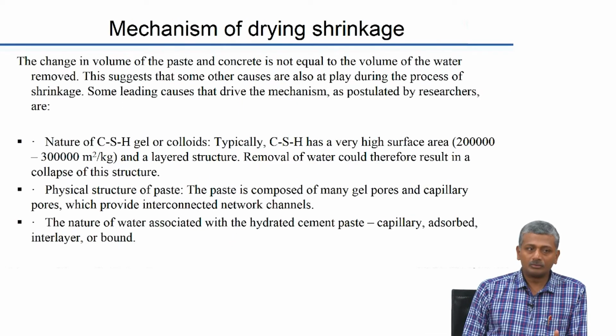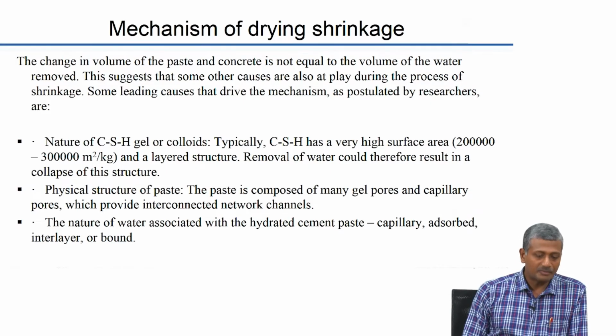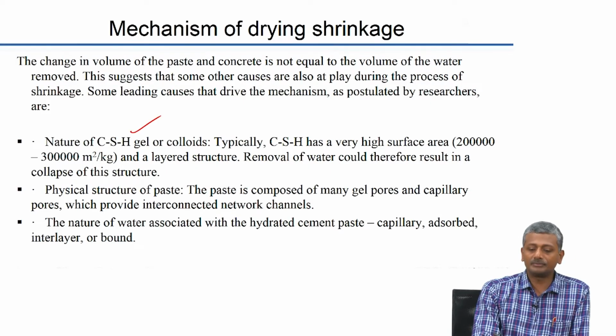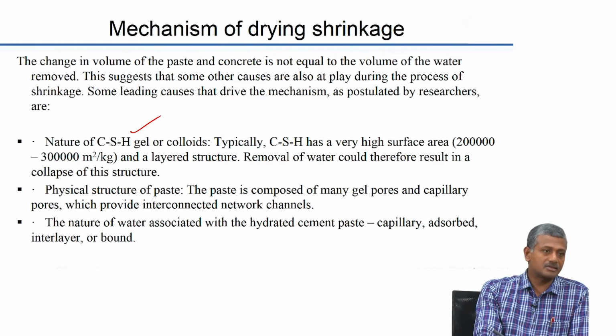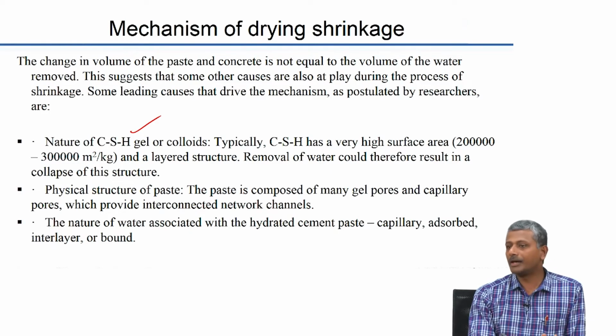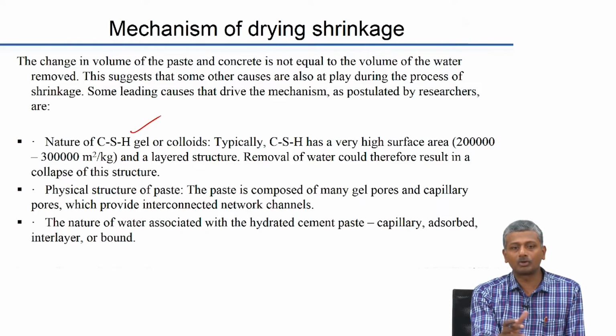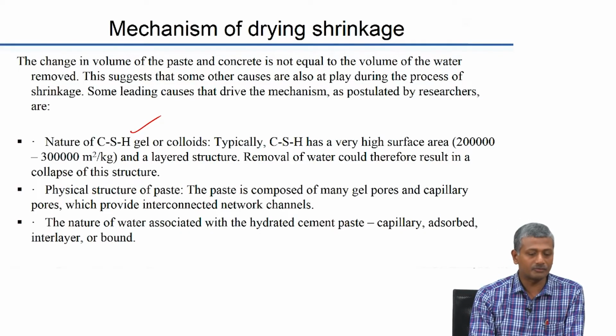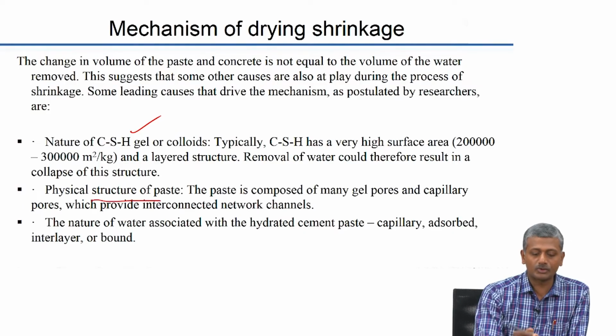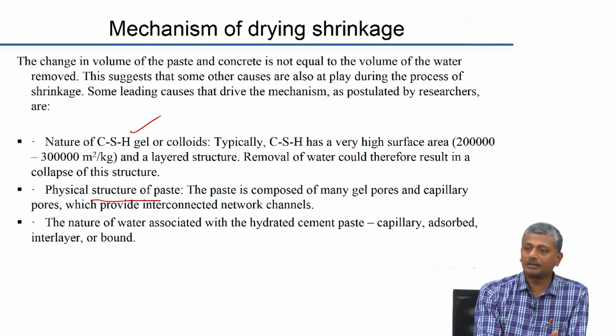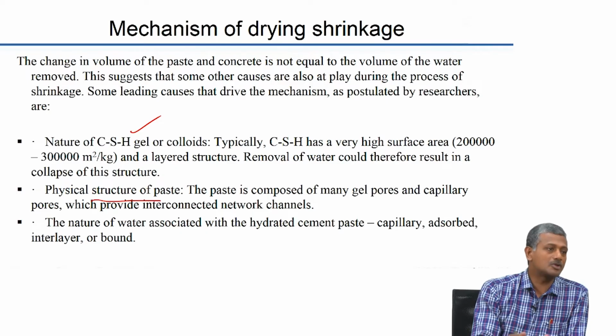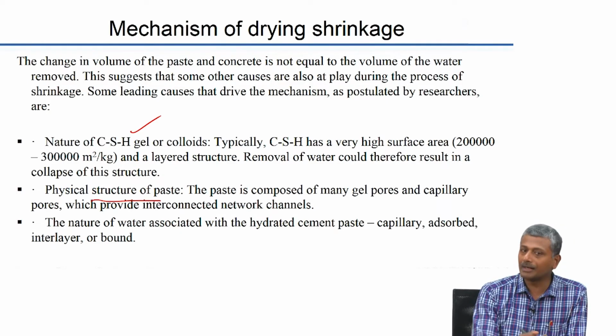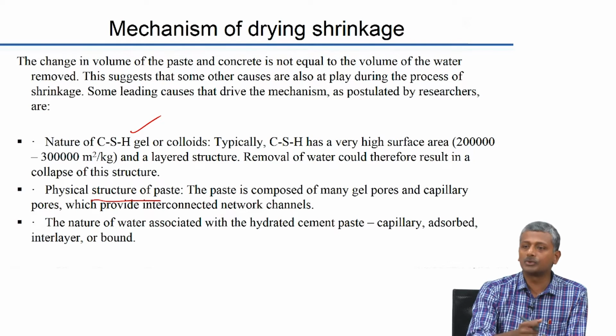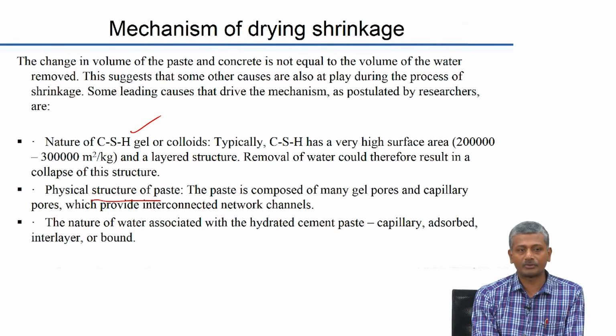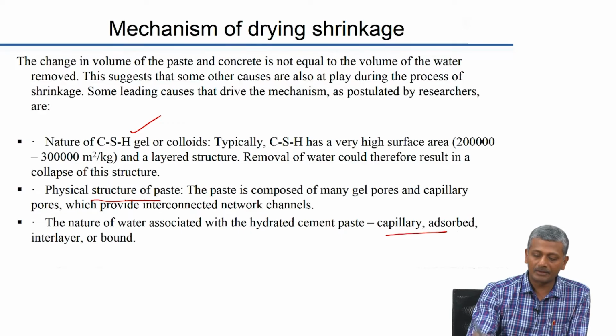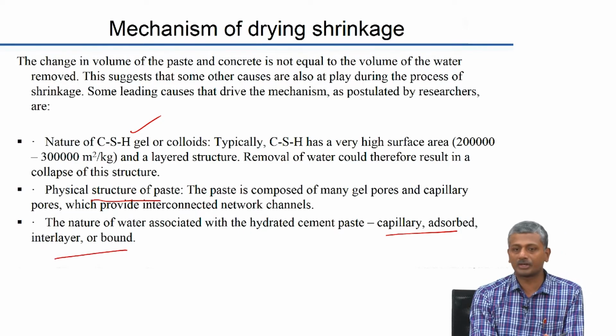Of course, if you really go into the depth of understanding why shrinkage happens, it is obviously because of the nature of CSH gel. We have also seen the structure of CSH as described by the Feldman-Sereda model, and when we were discussing that, we also saw what type of water would really lead to a high level of shrinkage. The physical structure of the paste is also responsible for shrinkage. Again, the interconnectivity of the porosity determines how much of this water can actually get out of your system. The more interconnected the pores, the greater the extent of water loss from the system.